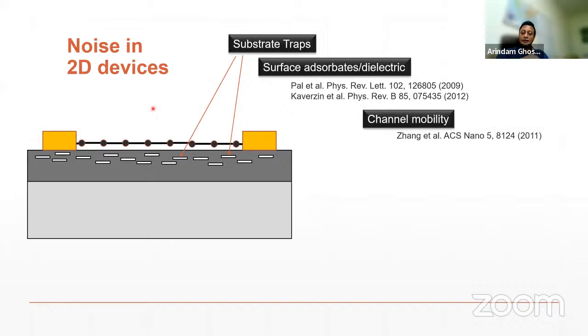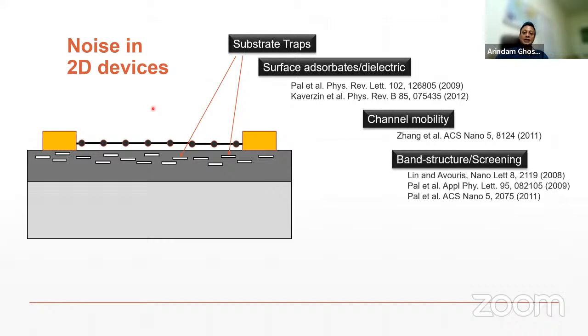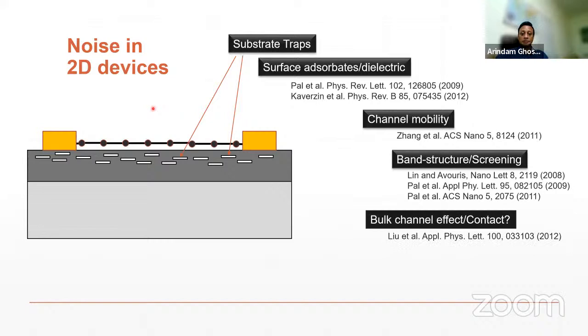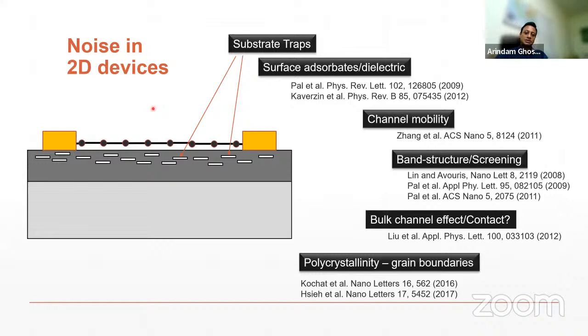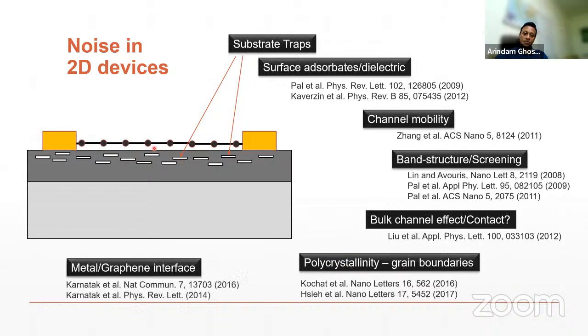Then we have the mobility of the traps. If the graphene is not mobile, it's not very pure, then you have additional noise. The band structures, the band gap of graphene, bilayer graphene, for example, can lead to additional noise. You have got bulk and channel contact effects, crystallinity of the graphene, grain boundary. These are all our work. Crystallinity means if there are grain boundaries in graphene, that leads to additional noise. And Paritosh showed very nicely that the metal graphene interface can also lead to additional noise.